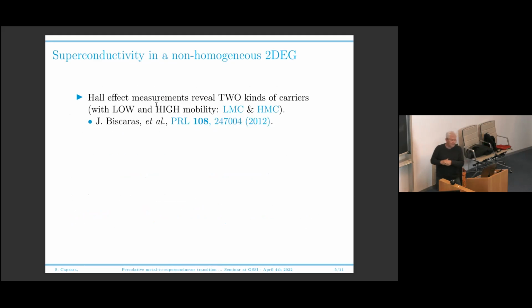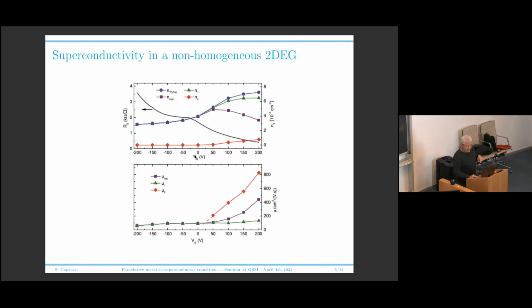So the Hall effect measurements reveal the presence of two kinds of carriers with low and high mobility. What is interesting is that the low mobility carriers represent the majority of the carriers in your system, but they have a very low mobility. And then at a certain gating around zero, the high mobility carriers, which are a minority fraction of the carriers, appear. They have a very high mobility. And it seems that at this interface, superconductivity appears together with the appearance of the high mobility carriers.